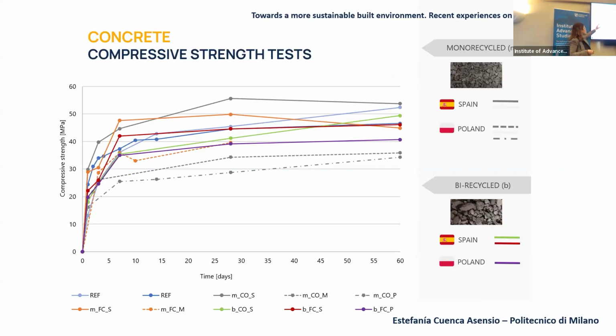And here you can see in this graph compressive strength compared over a long time. The results are quite good, as I told you from the table, which was the ultimate peak. But here it is quite good and, let's say, similar. The better one was this, as I told you in the last slide. But for example, the green one, the double recycled coarse only from Subterra, was a little bit worse in the early stage, but then it increased, maybe because we need more time to hydrate the cement particles and so on. So the green one was a little bit worse, but then we have a good performance after 60 days.